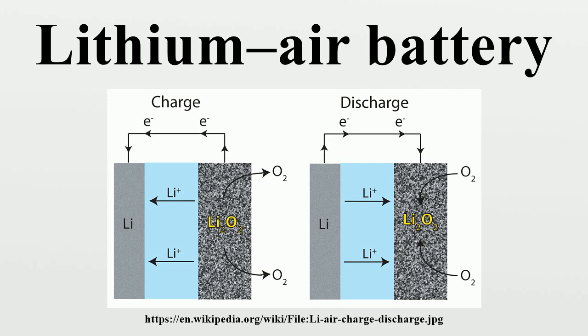The carbon cathode is usually made of a high surface area carbon material with a nanostructured metal oxide catalyst. A major advantage is the spontaneous formation of a barrier between anode and electrolyte that protects the lithium metal from further reaction with the electrolyte. Although rechargeable, the Li2O2 produced at the cathode is generally insoluble in the organic electrolyte, leading to buildup along the cathode-electrolyte interface. This makes cathodes in aprotic batteries prone to clogging and volume expansion that progressively reduces conductivity and degrades battery performance. Another issue is that organic electrolytes are flammable and can ignite if the cell is damaged.